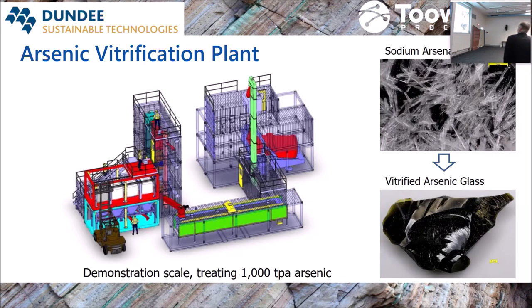Back end on the vitrification: as I said, we're looking at lots of different ways of fixing the arsenic at the back end, but we've done some work with Dundee Sustainable Technologies in Canada. They've been developing a vitrification process for arsenic trioxide dust from the smelters, and they're actually building a demonstration scale plant, being built and commissioned in Namibia at the moment, at the Tsumeb smelter. Basically, it's a bit like volcanic glass or obsidian. It's chemically binding the arsenic phases, whether it's arsenic trioxide or sodium arsenate, and then they're adding iron and some other things to make sure that it's not just chemically bound but also encapsulated in the glass. Extremely stable, and meets current TCLP and world environmental standards, and is likely to meet standards in 5, 10, and 20 years time.